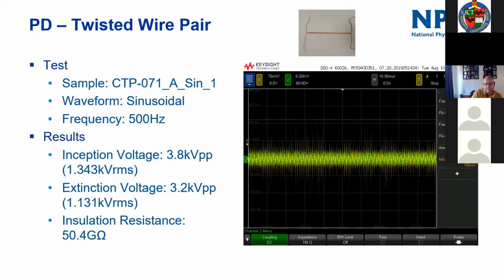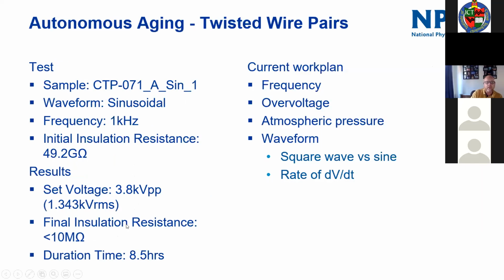So it's above 1000 volts, but it is still below 1500 volts RMS, which is an interesting figure, which we'll talk about a little bit later. Once you set the PD up, it actually continues as the voltage drops. And so in this particular sample, the extinction voltage, that's the voltage at which PD stopped being measurable, was down at 3.2 kilovolts peak to peak. And at this point, this sample has an insulation resistance of about 50 gigaohms.